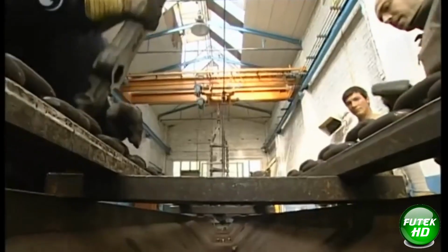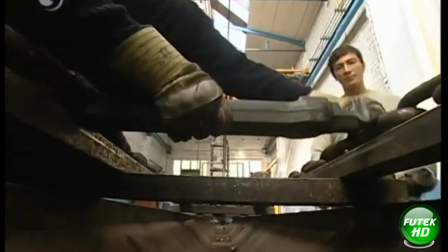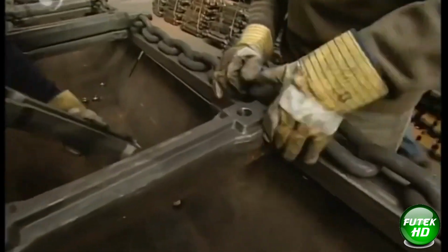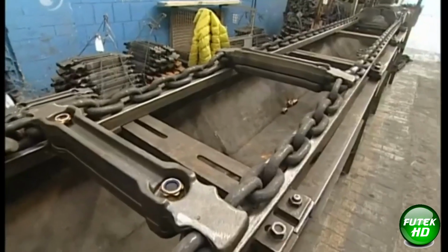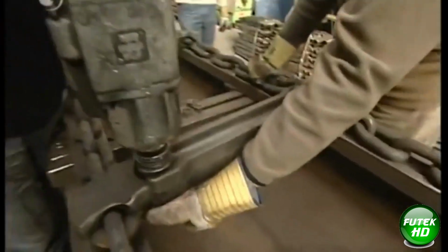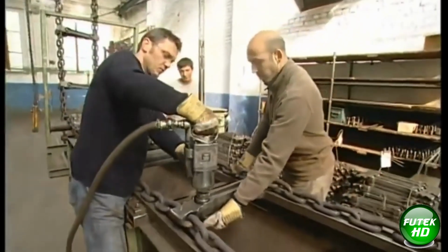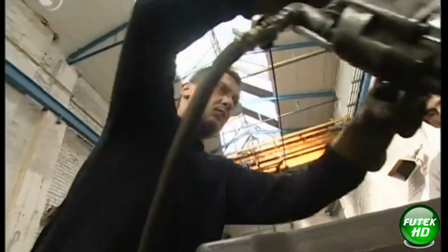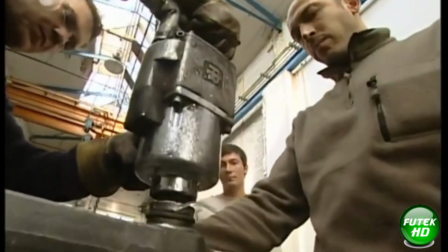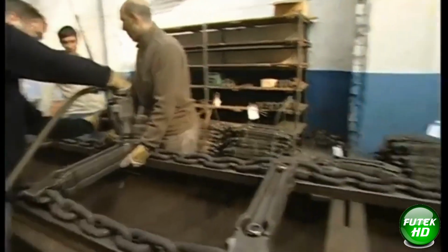Once the chains are assembled, they are subjected to rigorous testing. Each link is measured and, if necessary, adjusted to within 1/10 of a millimeter. The chain is then subjected to a tensile test, where it is stretched by several hundred tons of force. The goal is to ensure that the chain can withstand extreme stress. In one such test, a chain was stretched by about 1 centimeter under nearly 100 tons of force, but it only broke when the force reached 253 tons, proving its durability.